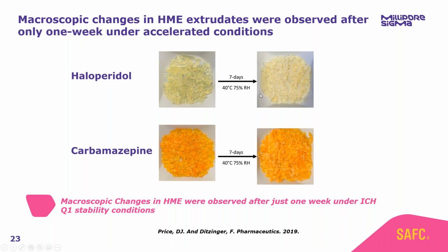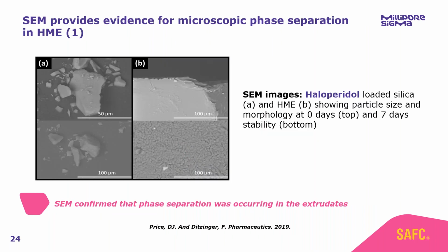We were pretty confident that we had a homogeneous distribution of our molecule inside the polymer. However, after only 7 days under these accelerated conditions, we no longer had a transparent extrudate, but instead an opaque extrudate. We can no longer see through our polymer, we no longer have a solid solution, and this is highly indicative that we have that phase separation behavior that I previously introduced. And that's exactly what we observed in our scanning electron microscopy images.